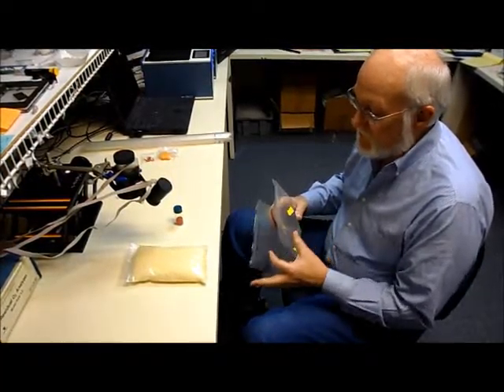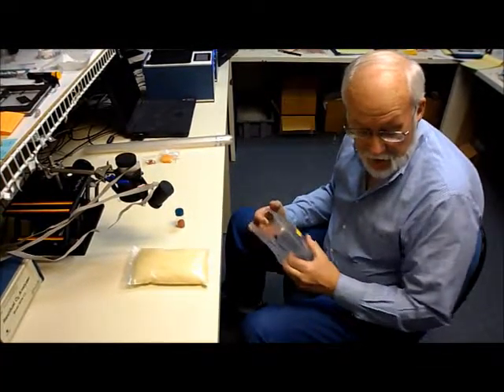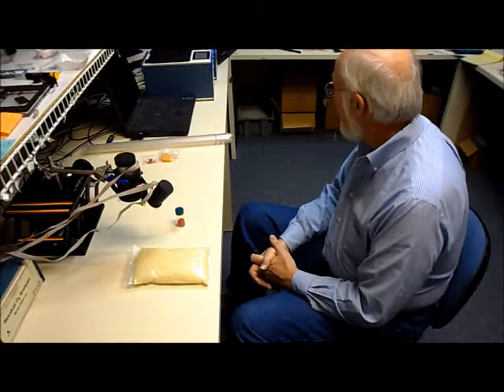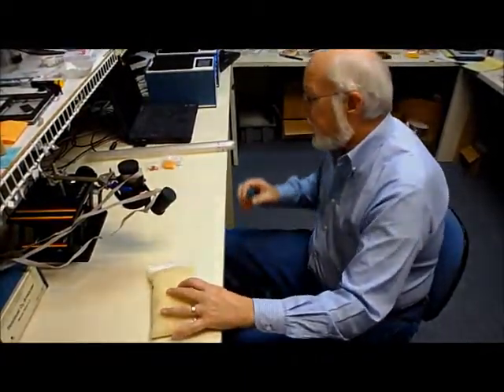But these materials that are oxygen sensing, I wanted to show exactly what they can do by virtue of a demonstration using, I'll just use a black light. We are typically measuring the oxygen with a meter. I will give you an example whereby the oxygen is going to be modulated with just a nitrogen stream under a black light. I think that will give a good representation of the nature of the responsivity of the material and how it is reversible, going back from a response of luminescence in a low oxygen and a high oxygen form. So we'll take a break and I will get the UV light out and give you that demonstration.